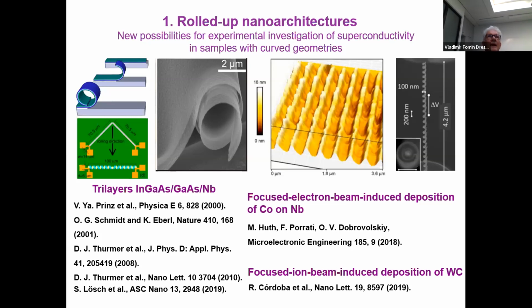Here in the left panel, you see a sketch of the method which is linked to using some ultra narrow membranes, for example, bilayer or three layers, which are put on a substrate using a sacrificial layer. And when this sacrificial layer is etched out, the strain which develops in the membrane due to mismatch of crystal lattices tends to deform this membrane, leading to the scroll. If the scroll continues, you can arrive at one tube-like structure or even radial superlattices.